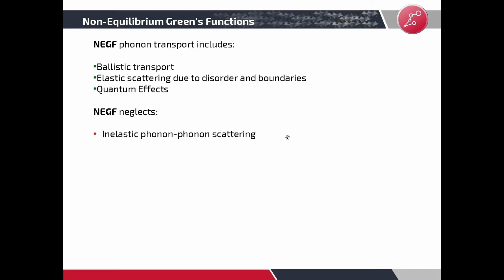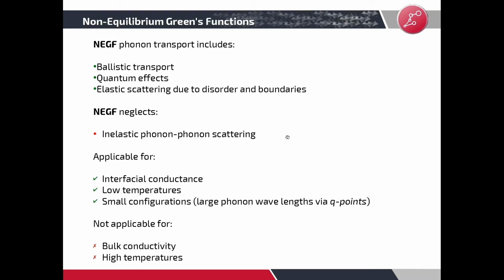So the NEGF phonon transport technique is particularly applicable for interfacial conductance, because here typically elastic scattering at the interface provides the largest contribution to the thermal resistance of the interface. Due to the full inclusion of quantum effects it is applicable at low temperatures, and you can also use small configurations. That means you do not have the finite size problems that you have in the non-equilibrium molecular dynamics technique.